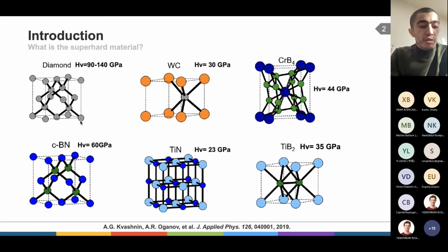But most of them are high pressure phases, like diamond and cubic boron nitride. And for producing other ones like tungsten carbide, we don't need high pressures. We need high temperatures. This is an advantage, but the disadvantage is a very low Vickers hardness in these materials. But there are also some classes of materials which possess really high Vickers hardness, and the perspectives of using these materials are very high, and it's important to develop new types of materials of this class.